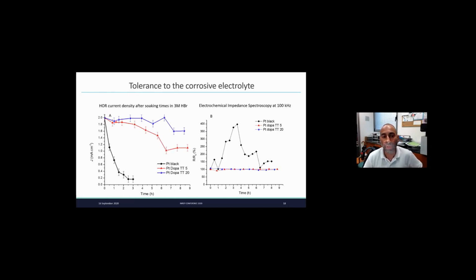And so what we've done is testing the electrodes after a few times, so after a few hours. So in black here, without coating, it's simply decreasing very fast. But when we have this coating, then it's pretty stable. The impedance also is very stable, showing that you don't have any film that is formed on the surface, mainly the bromide.